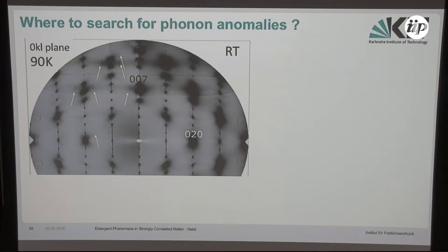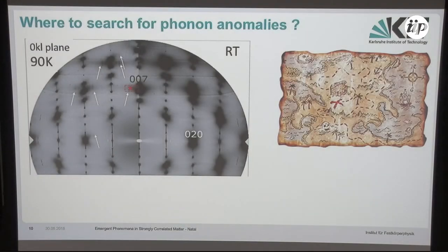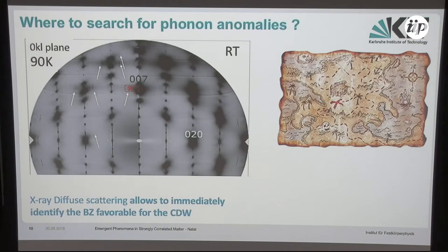We took a map of the reciprocal space using diffuse scattering at room temperature and then at 90K, and you see that at 90K we saw satellites coming up that correspond to the charge density wave. These are really the 2D charge density wave, and the idea was that we just go where these satellites are the strongest, and this is where we have the highest chances to see phonon anomalies. So this was really like a treasure map. It tells you where to look in the reciprocal space.